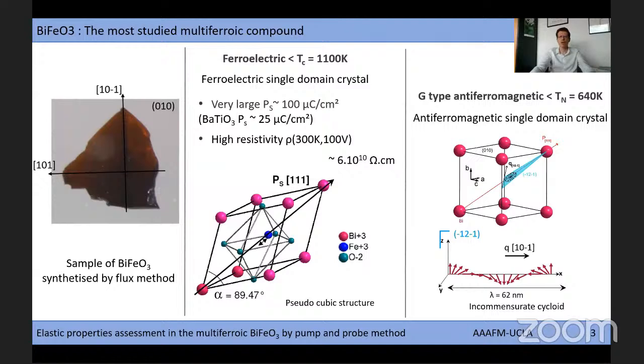BiFeO3 is also antiferromagnetic below 640 K, and due to the Dzyaloshinskii-Moriya interaction, the spins form a cycloid in the (-1 2 -1) plane.